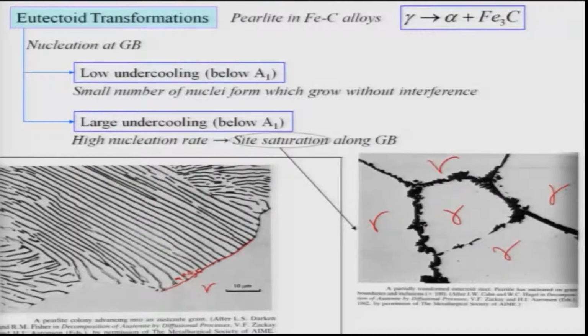Then these colonies grow inside the grains. It can also happen within the grains, if there is a compositional inhomogeneity or some defect structure present, like dislocations or voids or vacancies. It is possible, but preferentially nucleation happens along the grain boundaries, grain edges and grain corners. That is one important aspect.